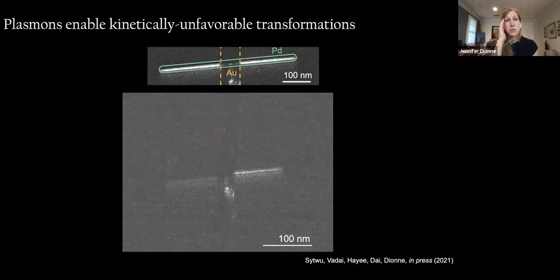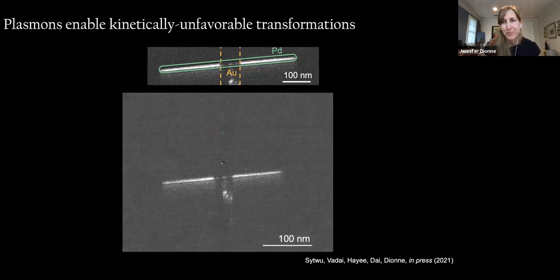So I think this is extremely exciting because here, by virtue of exciting localized surface plasmon resonances, we can actually make more of our catalyst surface catalytically active and basically enable what otherwise would have been kinetically unfavorable transformations. And this paper is in press. It should be out in about a week.